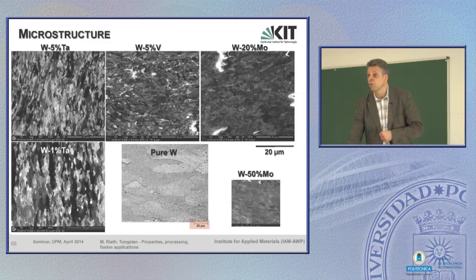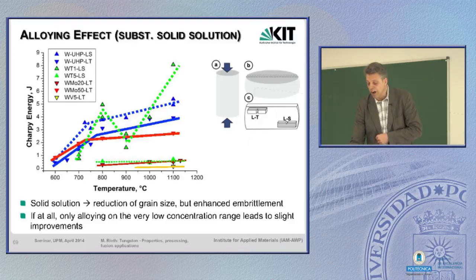So in the end, what would we expect with a finer grain? That's a classical hardening mechanism, it makes the material harder. And if you compare all these several materials with this blue line and dotted line as a reference, that's ultra high purity tungsten specimens, and all these are the solid solution materials, you see they are much more brittle, so in principle nothing was won by this